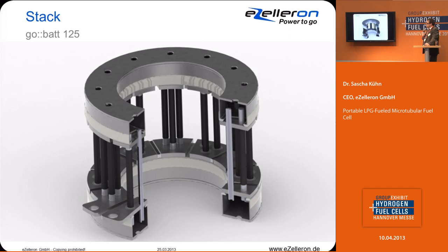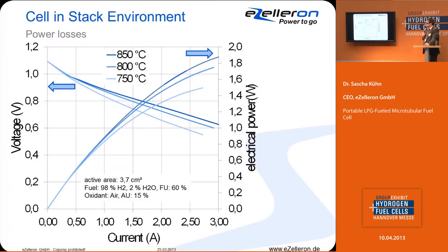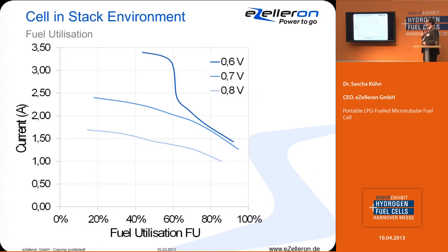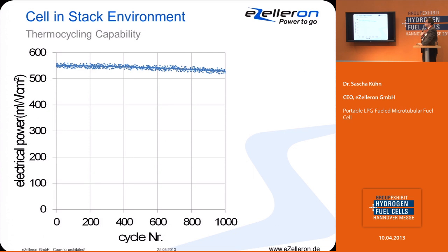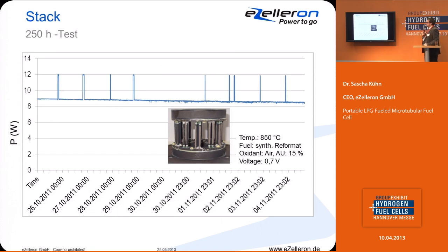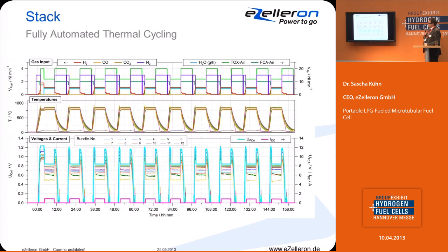I'll show you some pictures about the system development. This is, for example, a stack of our go::batt 125, which is a ring stack. The cells in the stack environment have lower energy densities, but still deliver more than 1 watt per tube, which is higher than any other microtubular developer can do. We have a very good fuel utilization. Thermocycling capability is excellent. Here you can see 1,000 cycles at a degradation rate of about 3%. In the stack environment, we have a higher degradation rate, but still in the limit that we need, and we can also thermocycle the whole stack at our automatic thermocycling test rigs.